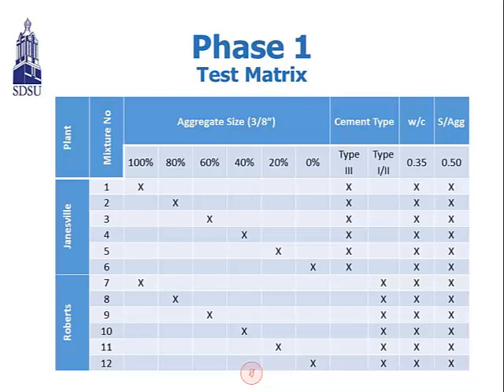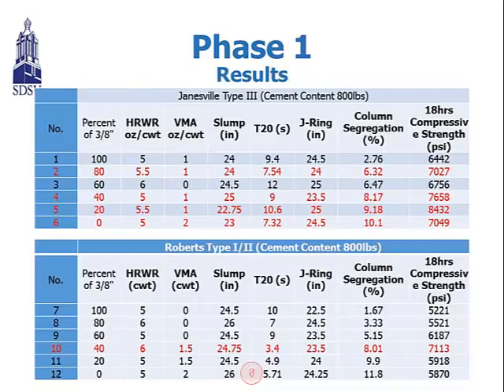So as I mentioned, we used two plants, Janesville and Robert. And we have 12 mixtures, and each mixture varied depending upon the aggregate size: mixture 1 is 100% 3/8 inch. And mixture number 2, for example, is 80% 3/8 inch and 20% 3/4 inch. And we use cement type 3, a water cement ratio of 0.35, and a sand aggregate ratio of 0.5. So using the test matrix, we conducted the testing, and we got the results.